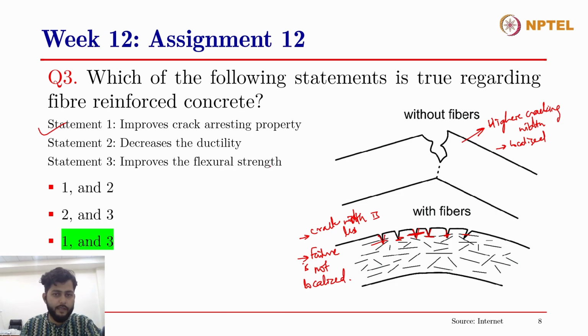Including fibers arrests the crack propagation in concrete. And again, it increases the ductility. So the second statement is wrong. And finally, it improves the flexural strength as well, because you impart more ductility to it, and you also restrict the crack propagation in the concrete. Therefore, you allow the concrete to take a higher load in the case of flexural load application. So the flexural strength is also improved in the case of inclusion of fibers in concrete. Right. So the correct answer to this question is 1 and 3.